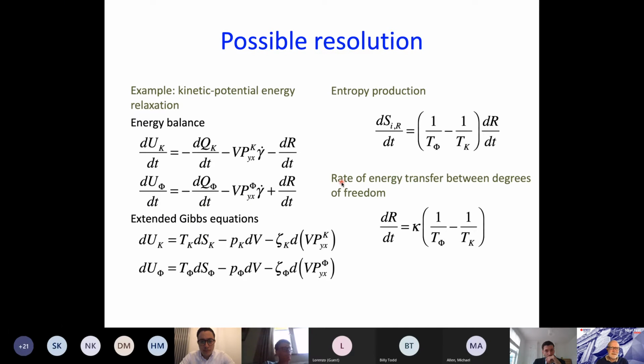So we can understand all this through an idea of having different energy balance equations for the different degrees of freedom in the system. So for example, let's say we only had two heat baths that we could define, a kinetic energy heat bath and a potential energy heat bath. And we could have heat transfer. So this would be the rate of heat transferred due to heat flux. Let's say we still had a spatially varying system. So we could have a rate of heat absorption at a point through the kinetic part of the heat flux. And we could have the heat generated in the kinetic degrees of freedom by the shear. And we could also have a term relating to energy transfer in and out of the kinetic energy heat bath. And likewise, we could have a similar equation for the energy balance of the potential energy bath.